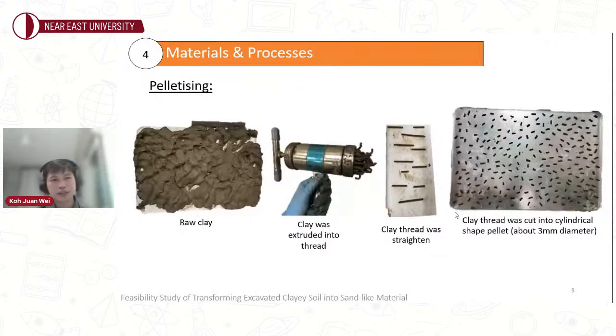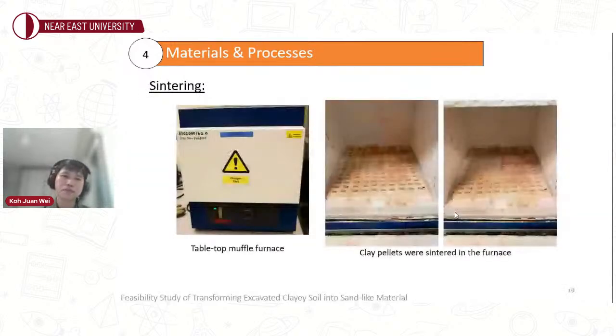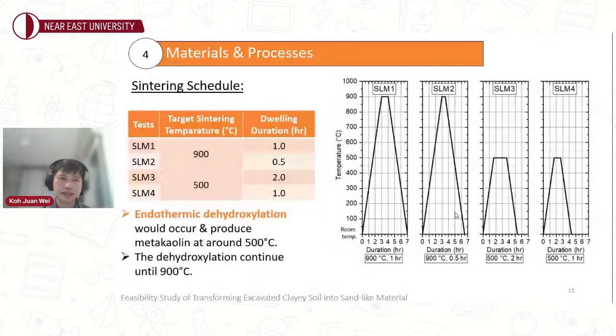First is the raw clay, and we use a special extruder to extrude it into thread-like form and chop it into about 3 mm in diameter. This is the tabletop muffle furnace that we use to sinter. And this is the sintering schedule used in this study. We conducted 4 different series, where the sintering temperature and duration differ. SLM1 and SLM2 were sintered at 900 degrees C, with durations of 1 hour and half an hour. For SLM3 and 4, a lower sintering temperature of about 500 degrees C was used, with a duration of 2 hours for SLM3 and 1 hour for SLM4.